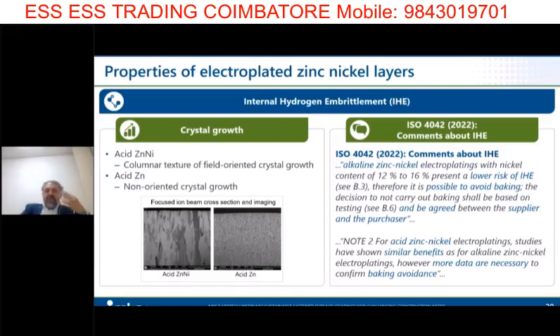The reason for this, don't be scared of this picture on the left side of the screen. In general terms, the main reason is the columnar texture of field-oriented crystal growing in zinc nickel that gives the permeability of this layer for the hydrogen. So the hydrogen can go out much easier.